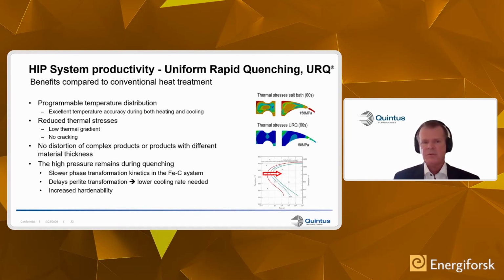And also, one thing that we do is that we can keep the pressure at a certain limit during quenching, which will push the transformation curves to the right, so that you can avoid any type of phase transformation that we need to.